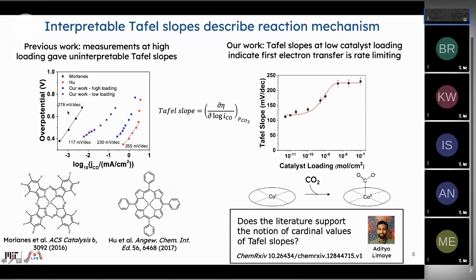So historically in the literature, shown in the black points here and in the red points on the far right-hand side, one has observed Tafel slopes that are relatively large for cobalt macrocycles. So for a perfluorinated cobalt phthalocyanine, as well as the closely related cobalt tetraphenyl porphyrin. And these Tafel slopes essentially leave one with very little mechanistic understanding. But if instead you use the lower loadings that we have shown in our work, shown here on the purple trace, one can actually obtain a Tafel slope which makes sense of 120 millivolts per decade.